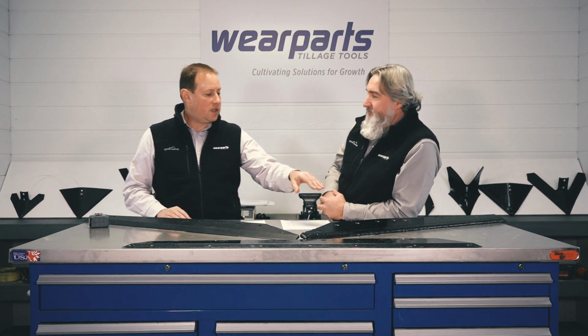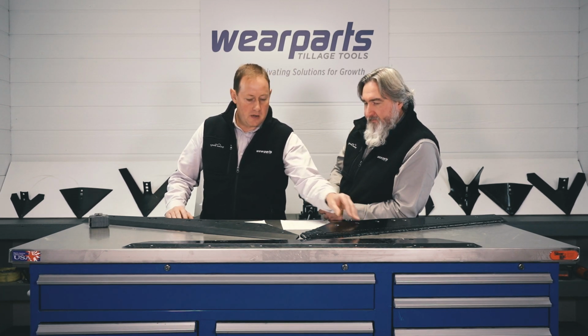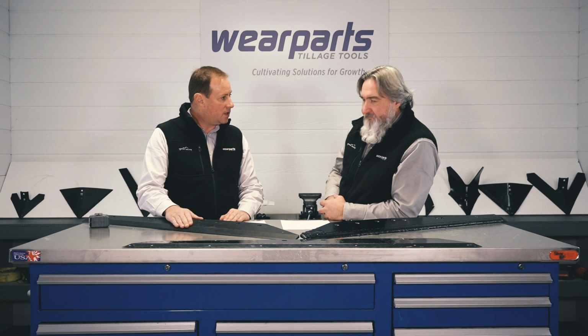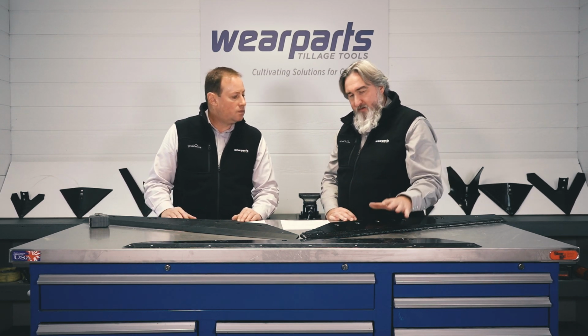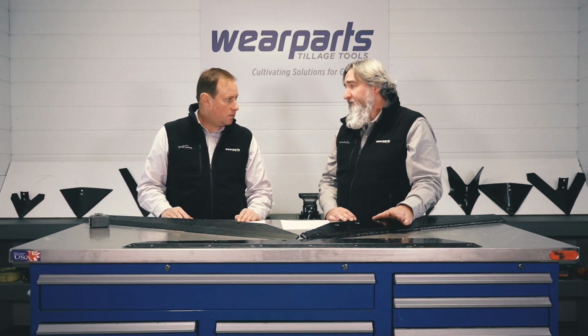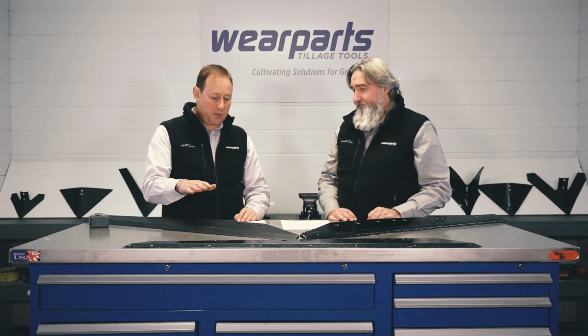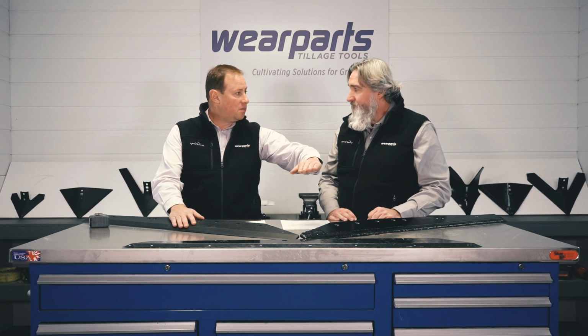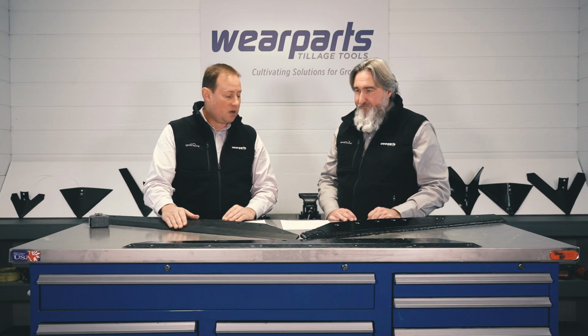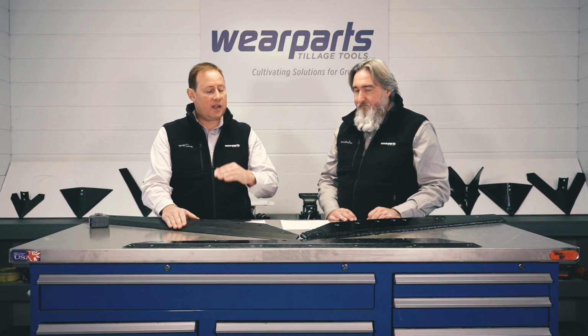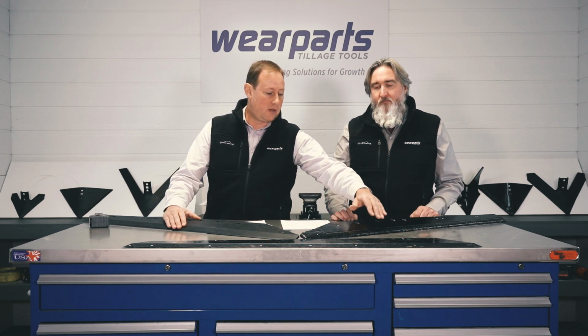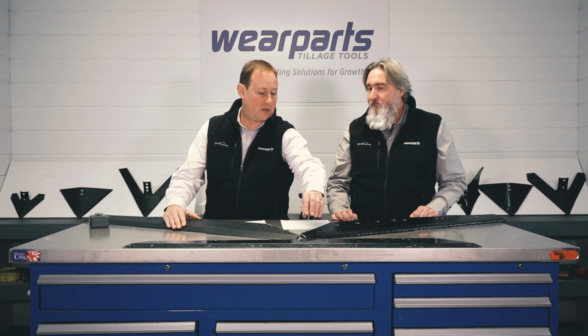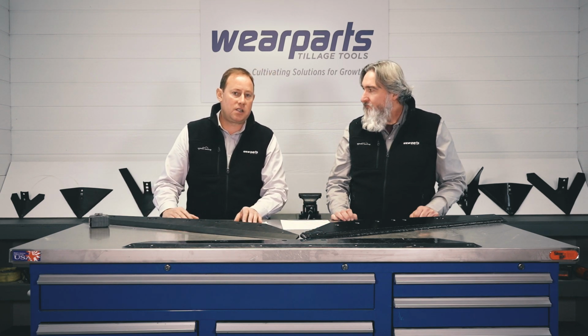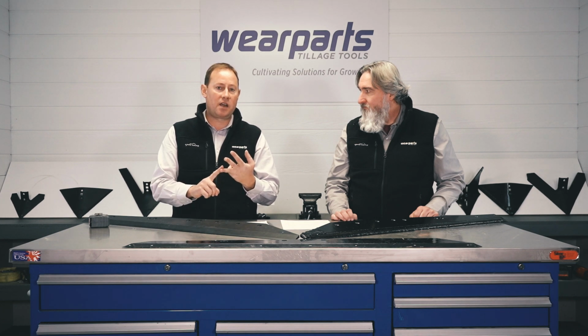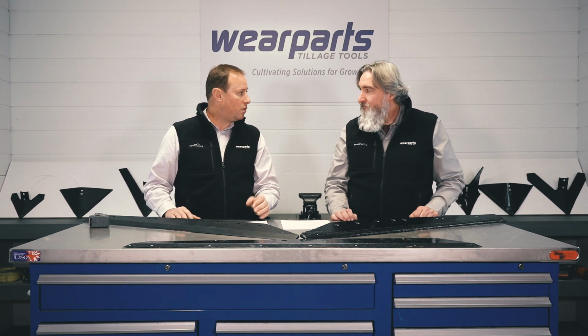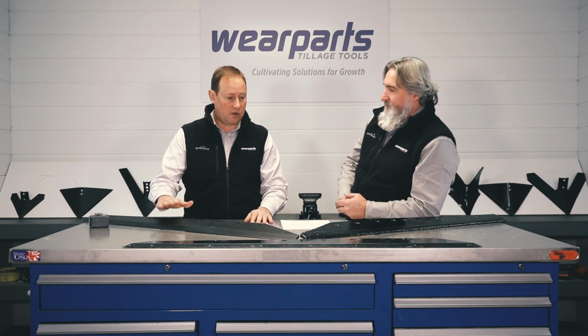Gotcha. And on our hard face peanut blades, how much longer wear life is that than the standard plain? Are you seeing double or triple the wear? You're typically going to get 2 to 3 times at least the wear out of a hard face blade versus a plain one. So when comparing Wear Parts plain blades against plain blades of competing brands, we're seeing a substantial increase in wear because of our material composition and tempering. And on top of that, if you want even longer wear, you can go with the cold metal transfer process wings with the oxy-fuel nose on our peanut blades. What that gets you is much longer wear life, reduced downtime, resulting in lower cost per acre. So it's a win-win situation for the peanut farmers out there. These are used for peanut harvesting.